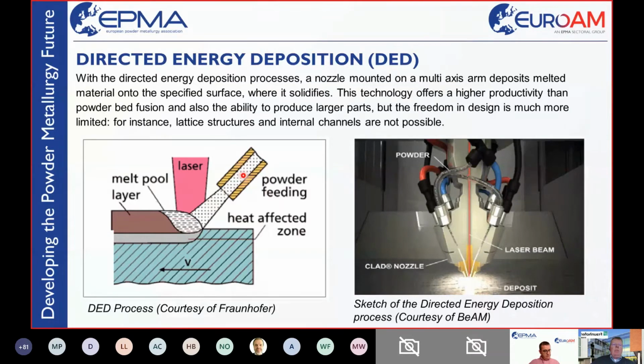So you have a powder feed here and a laser melting the powder, and then you have a welding process, a clear welding process. And if you use a 3 or 5 axis manipulating system, you can end up with very large and very complex structures. A limit with DED is the production of very small, very fine lattice structures or internal channels. There, DED is definitely limited compared to the other processes mentioned before.